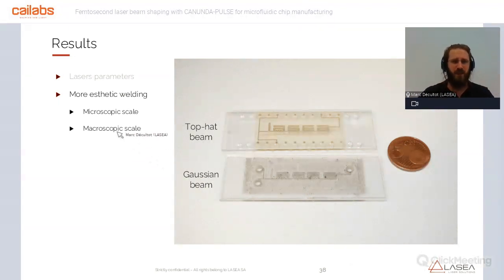The more aesthetic welding aspect is also visible at microscopic scale. Here you can observe a microchip sealed with a top hat beam and a microchip sealed with a Gaussian beam. It's important to note that here we have transparent materials, transparent polymers. So we make weldings of transparent polymers without any absorbent layer. That is the difference from continuous wave laser technology to seal microfluidic chips. Here we have a good result, as you can see with the top hat beam. The welding has a clearer aspect.